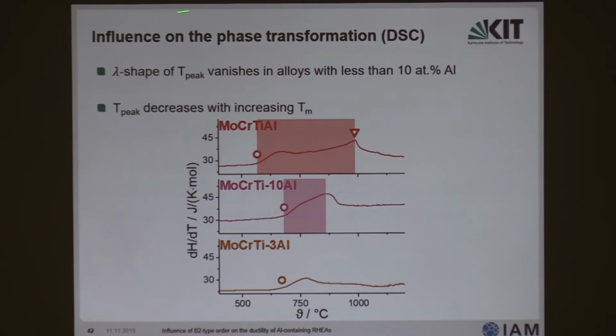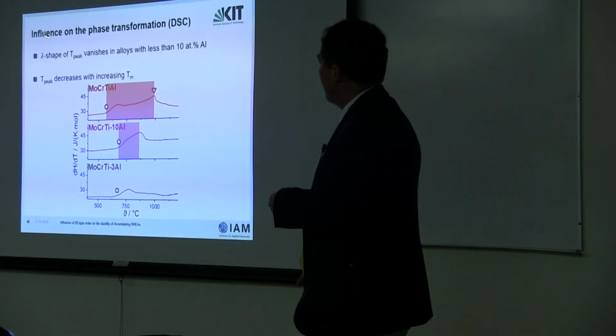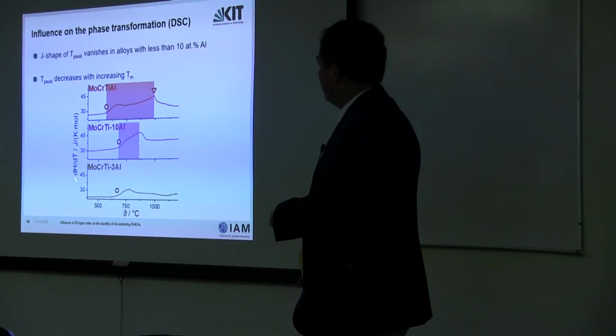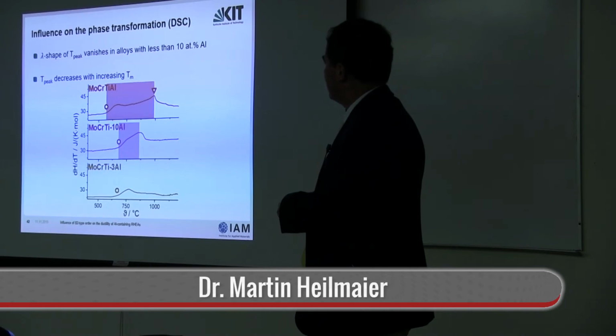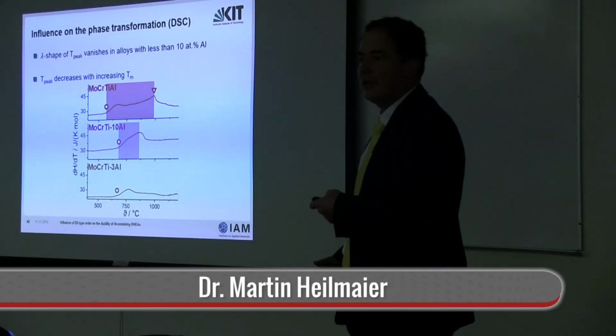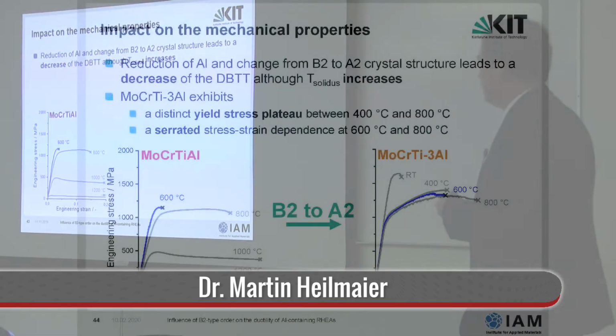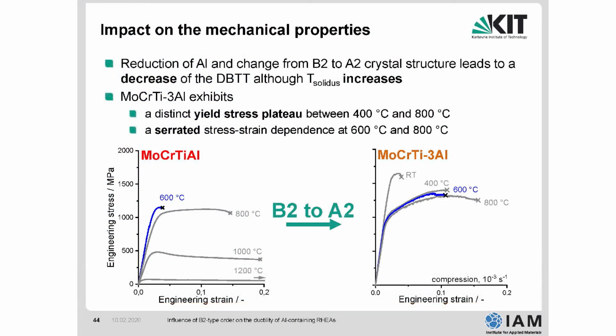This I skip. We can check by another microstructural characterization method, for example differential scanning calorimetry, whether we have an A2 to B2 order transformation. When you observe an ordering, you have this lambda-shaped peak here, which is gone in this case for this alloy. And here you can hardly see it. So alloys containing less aluminum than 10 at.% should not have ordering. So this was the plot shown before. And now, hurrah, we do have some ductility at room temperature.